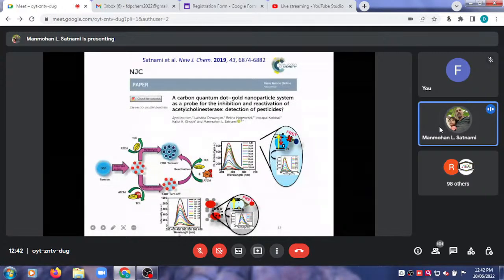So you can see from here, when the gold nanoparticle is interacting with carbon quantum dot, the fluorescence intensity is decreasing continuously. See here. Okay, and from the top right hand side, you can see the fluorescence spectra that the fluorescence intensity is increasing. So this is increasing because of what? Aggregation of gold nanoparticle. When it was the normal process, and when it was inhibited by pesticide, then reactivated by reactivators. So on the ground of this, we designed the sensor for the detection of pesticides.